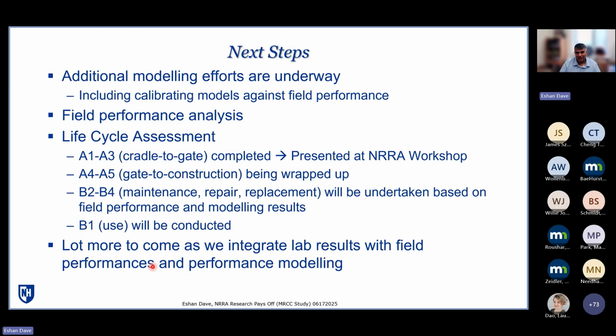So that's the next step. The next step is essentially, now that the MnROAD cells have started to crack, this January was the first time that we observed cracking. Not surprising in the control section with 58S-28. Now that data is coming in, we are actually able to compare the field performances to these indices to tell you which lab test makes more sense or gives you a better comparison, but also which modeling efforts can be more reliable in order to predict the performances when it comes to reflective cracking. So obviously that is an effort that's underway right now.